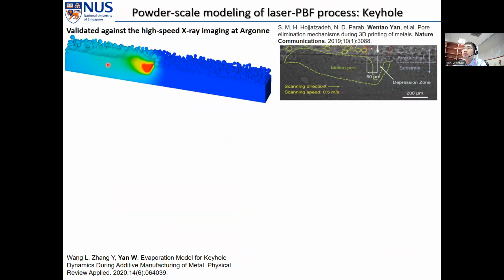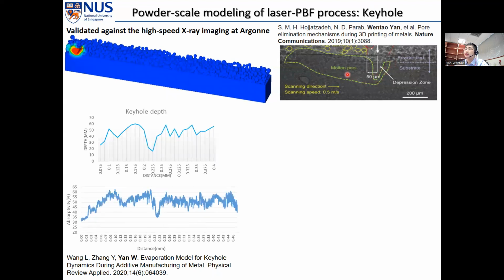This is the laser scanning case. In collaboration with Argonne National Lab, we also simulated this, and you can see the keyhole size and shape and the molten pool shape and size all agree well between the simulation and experiments. But more importantly, we can provide some information that can hardly be measured even at Argonne. That is the energy absorptivity at different locations.